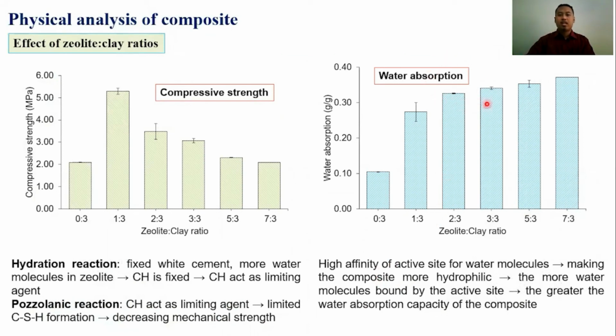On the other hand, based on the water absorption capacity test, we get a trend of increasing water absorption from the zeolite to clay ratio from 0 to 3 until 7 to 3. It can be explained that the high affinity of the active sites of the composite makes it more hydrophilic. So, the more water molecules found in the active sites, the greater the water absorption capacity of the composite.